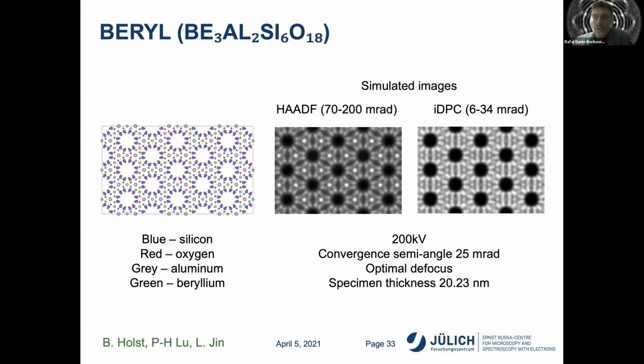The fact that the beryllium atomic columns are very weakly scattering is responsible for the fact that in high-angle annular dark field images, the beryllium atomic columns are invisible, whereas in a phase contrast image, in this case, simulated for the technique of integrated differential phase contrast, the beryllium atoms suddenly are visible. These are simulations with no noise included, and the beryllium atoms are halfway between the black channels.